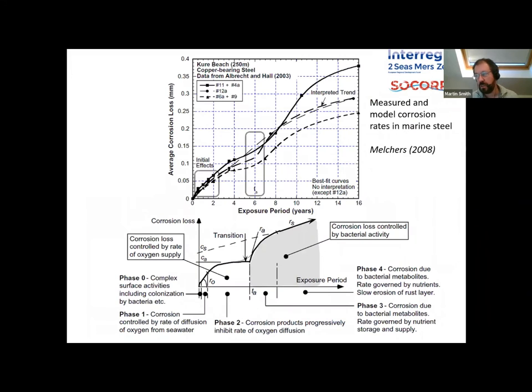When people have gone and looked at corrosion rates, so this is work by Melchers, published in 2008, what he's tried to do here is generalize what usually happens with marine corrosion rates. So we have initial electrochemical corrosion, we have colonization of the steel surface by organisms, and we get a corrosion rate that's controlled by the diffusion rate of oxygen from seawater.